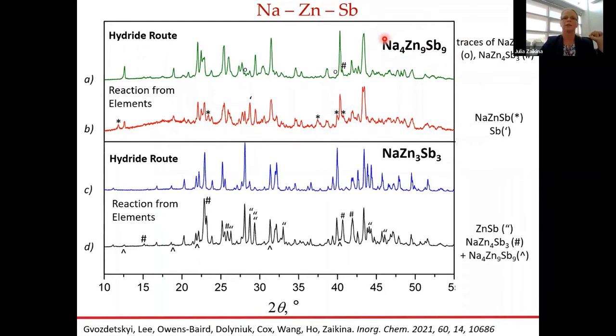And then similarly with the 133 phase, the reaction from elements gave us a very multi-phase sample. Zinc antimony, the binary one, is one of the impurities, as well as other ternary impurities. But the hydride route allows us to target that specific composition and make a pure sample, which then can be used to measure the properties of those compounds.